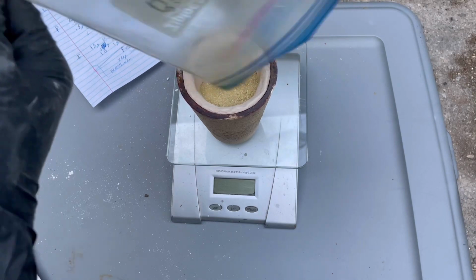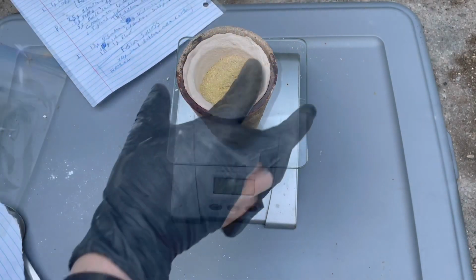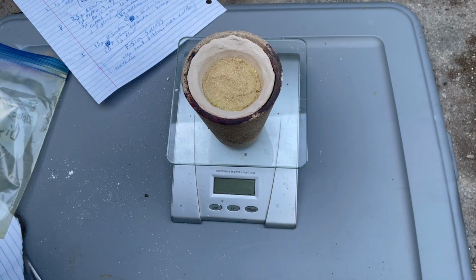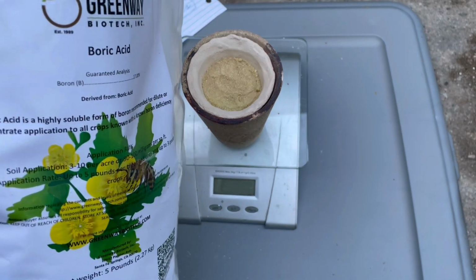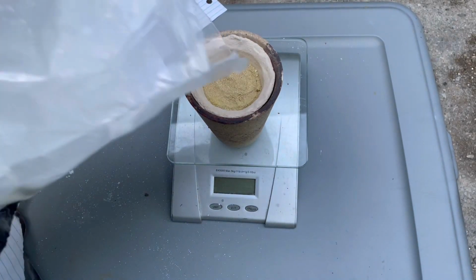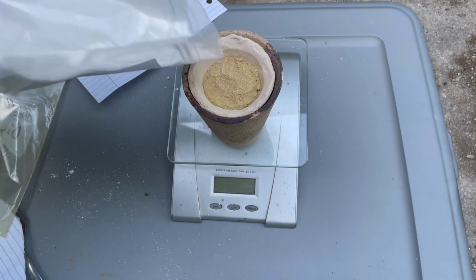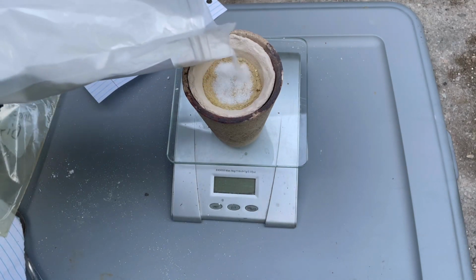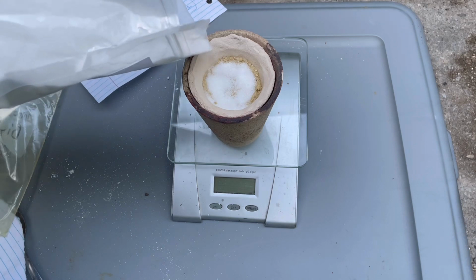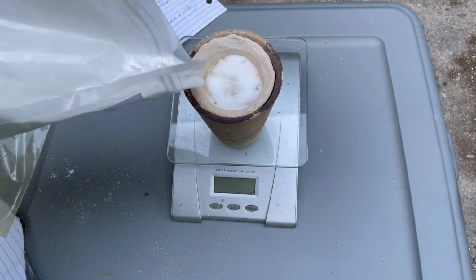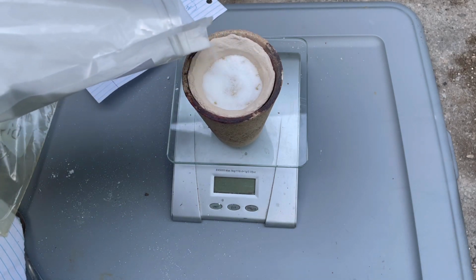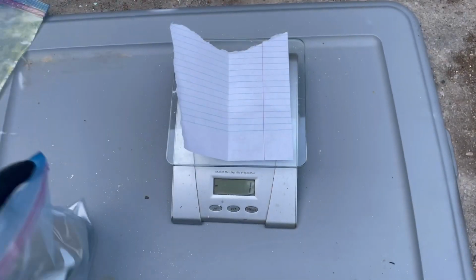Okay. It's about as full as I'd want it to be. Now all that's left is to cap it with a little bit of boric acid. The boric acid melts at a low temperature and will seal the mixture from the atmosphere before it gets too hot. There we go.